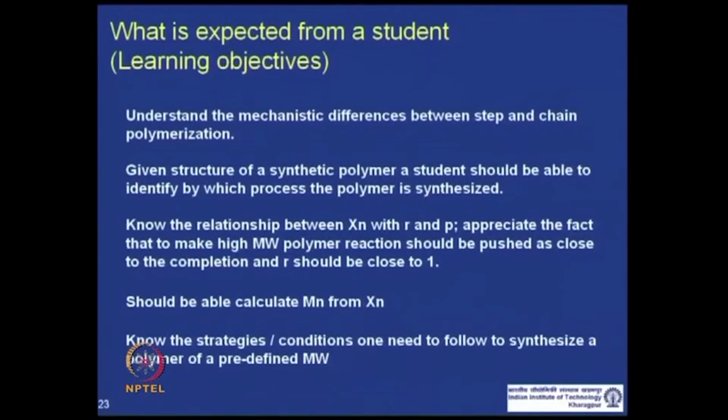If you want to control the molecular weight, if for some reason you want to target some molecular weight with both the ends having some particular functional group or no functional group, then you should know the strategies. If you want to have some functional group at the end of the polymers on both sides, then you should use the monomers containing that functional group in higher amount, and the ratio should be according to your target.